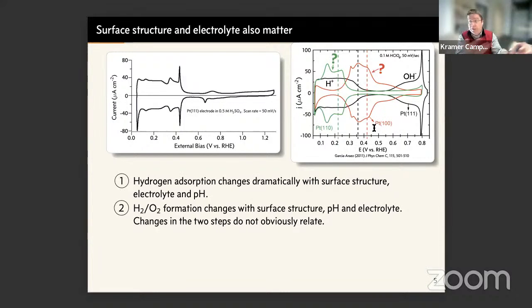The astute among you will also note that this black curve is labeled platinum 111 here, and on our plot it is also the platinum 111. The difference between these two situations is that the one on the left is in sulfuric acid, the one on the right in perchloric acid. And of course, this is a kind of classical non-interacting anion and interacting anion.